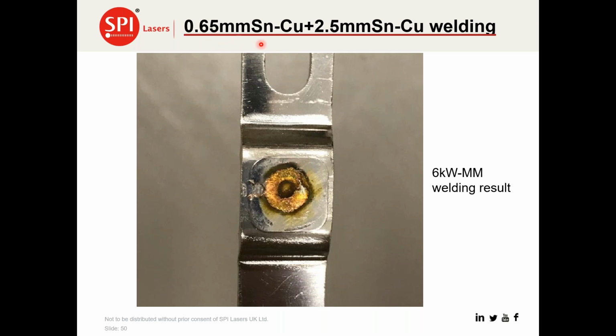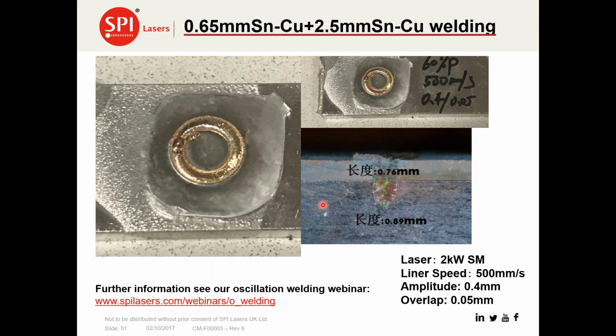This is another odd material, which is tin copper alloy welding. It has a propensity to soot and spatter. This is the result using a 6 kilowatt multi-mode fiber laser, and it's very difficult to get consistent quality. However, if you do this joint using an oscillation technique and a 2 kilowatt laser, it's half the speed, but in terms of the cycle time in this particular application, the welding speed didn't have a huge impact. But as you can see, the quality that could be achieved, almost zero spatter, bright welds, very consistent over the whole ring, with a good consistency in depth and interfacial area. This was something that the customer really liked.